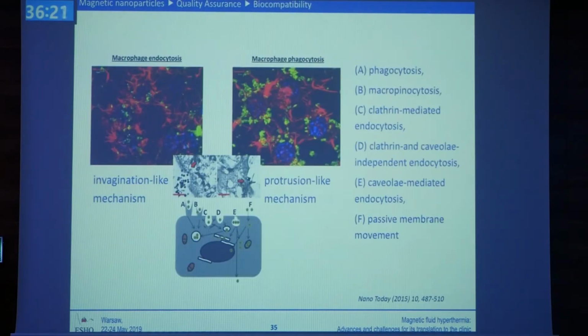I have to say that the mere synthesis, before we go to functionalization of the nanoparticles, is only nowadays under standardization. So you can have different groups following the same recipe, because these are recipes for creating nanoparticles, and then end up with nanoparticles with different physical characteristics. So if you go to the microscope, to the TEM, and you take a TEM picture, although they have followed the same recipe, you don't get the same result in different labs.